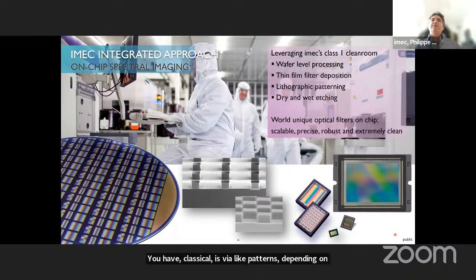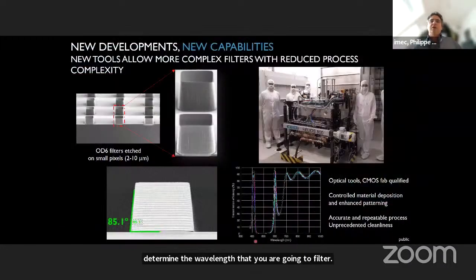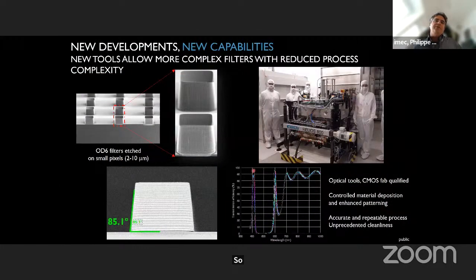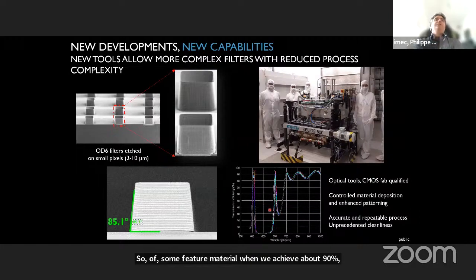Depending on the wavelengths that you want to sort, we apply different kinds of processes. And the control on all the layer thicknesses is extremely important because the direct physical thickness is going to determine the wavelengths that you're going to filter. So here, a classical example of a filter material where we achieve about 90% transparency at 400-something nanometers. You can see this is a typical layer stack that is being used.